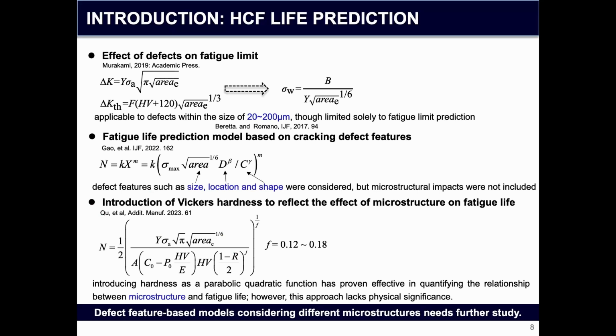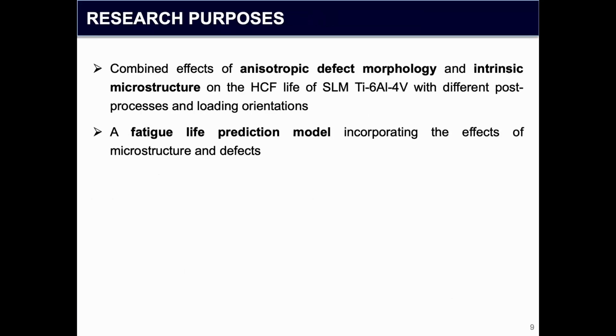And for the high cycle fatigue life prediction models, we do have several very nice models considering the effects of size, location, and shape of the defect, and also the microstructure. But the defect feature-based models considering different microstructures need further study. So one purpose of our study is to explore the combined effect of anisotropic defect morphology and intrinsic microstructure on high cycle fatigue life. And we also would like to develop a fatigue life prediction model considering both effects of microstructure and defects.